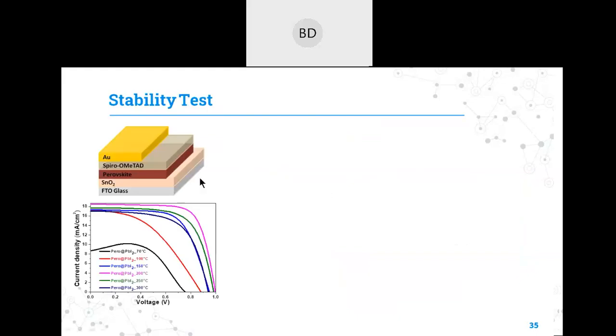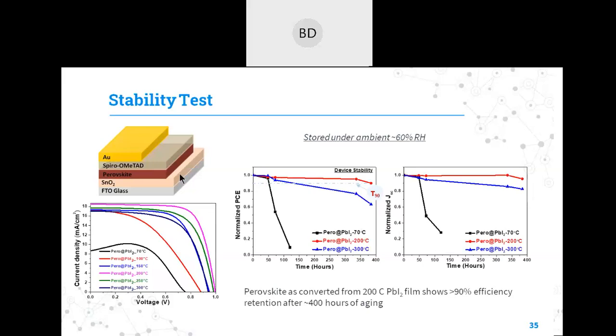The same perovskite films have been implemented into the device, and we have observed a significant increase in the JV efficiency for the perovskite film which is prepared at 200 degrees centigrade. We saw that the efficiency has been increased from 4% to approximately 13%. And we kept these devices under ambient conditions at 60% relative humidity, and we saw that the perovskite film which is prepared at 70 degrees centigrade has almost degraded within around 100 to 120 hours.